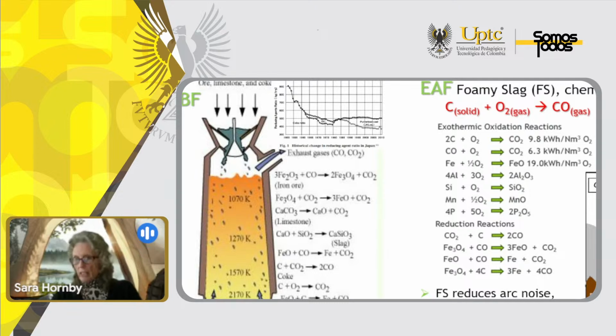In terms of the EAF, we use carbon for foamy slag and chemical energy currently. Now, the foamy slag is very important because it reduces the arc noise. It foams the slag, and because of the foamy slag, we have a greater surface area to react with the metal, and that gives us much faster reactions and allows us to increase productivity.